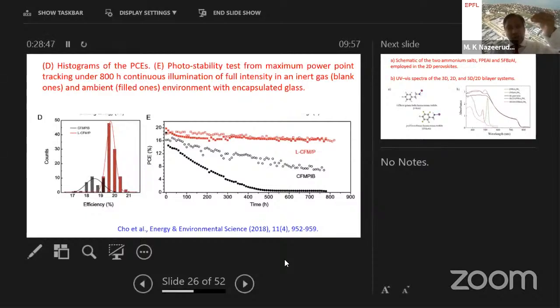Now both are overlapping. However, compared to the reference sample, the two-dimensional perovskite deposited perovskite solar cell shows extremely stable performance. So this is the beauty of demonstrating stable perovskite solar cells by interface engineering.